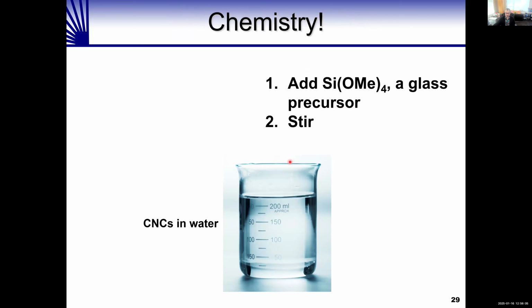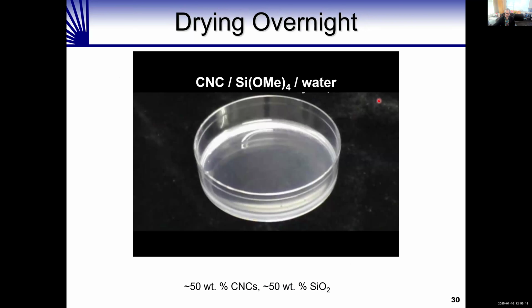Here's our chemistry: we take our beaker of cellulose nanocrystals in water, add tetramethoxysilane, that glass precursor, and stir it. Then we pour it into a petri dish containing cellulose nanocrystals, tetramethoxysilane, and water. All we do is leave this on the bench top and let the water evaporate. I'm going to show you a video of the water evaporating from this petri dish overnight.